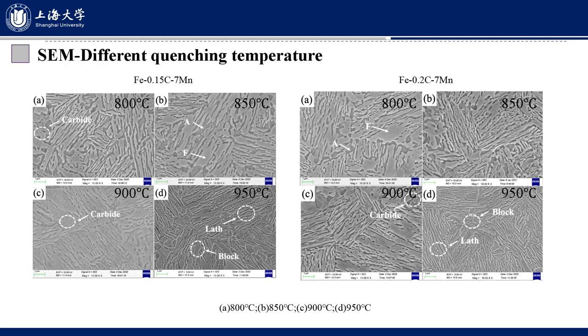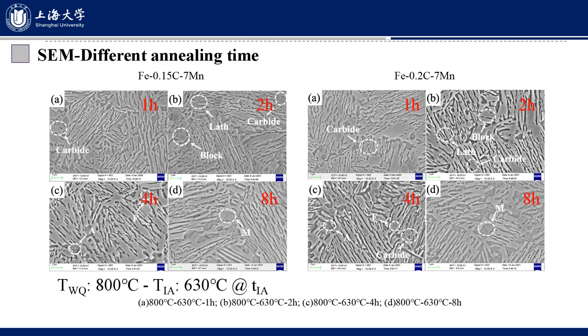This slide shows the microstructure of the steel for different quenching temperature cases. It's clear that the microstructure is mainly austenite and ferrite. And for the 950 degrees C case, lath-like austenite is obtained.